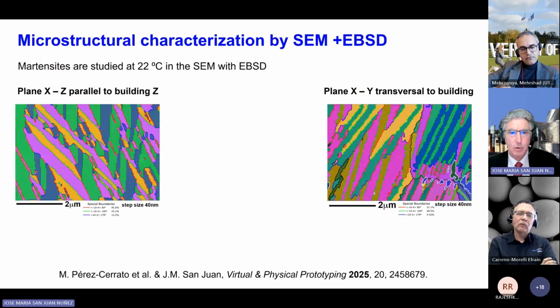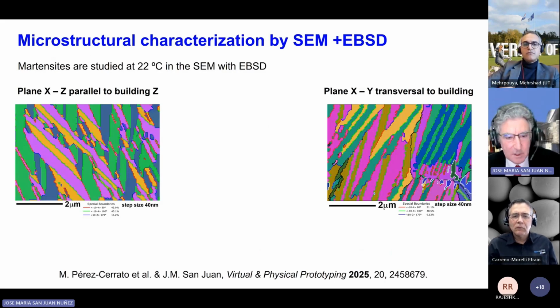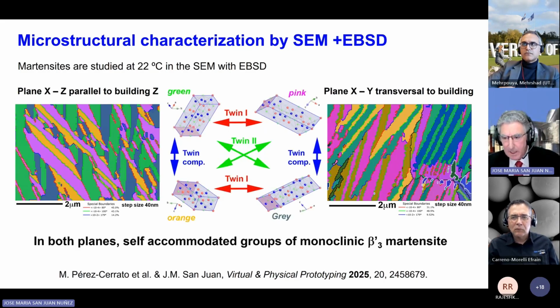Then let me move to the microstructure characterization. First, at room temperature, the material is in martensite. And then we have studied the martensite in both planes: the XZ plane, so parallel to the building direction, and the plane XY, which means perpendicular or transversal to the building direction. And I show you here the different martensite with different orientation. And in fact, these martensites are determined by electron backscatter diffraction and are identified, in both cases, as self-accommodated groups of monoclinic beta prime 3 martensite on different orientations and with the relationships corresponding to the theoretical background.